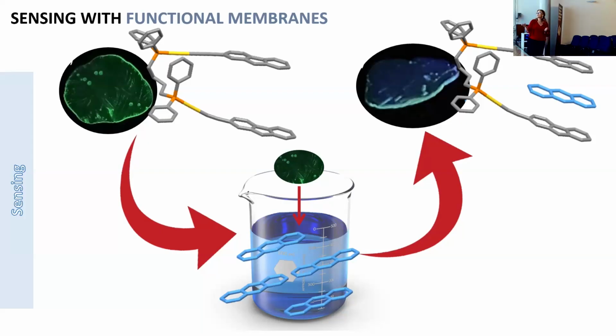So the idea was, if we have an aqueous solution with a contaminant, and we have our material with a determined luminescence, in this case yellow-green emission, if we dip our material in a contaminated sample, we can see if the sample is contaminated or not, because it produces a change in the luminescent colors. So this is really a simple idea, but it can be translated to really difficult places, for people in a discotheque who are offered a glass of water, well, not of water, but you would like to see if there are some contaminants or not, so you dip it and you say, maybe I will not drink it. So if you are seeing these changes in the emission. Okay, with this I finish.